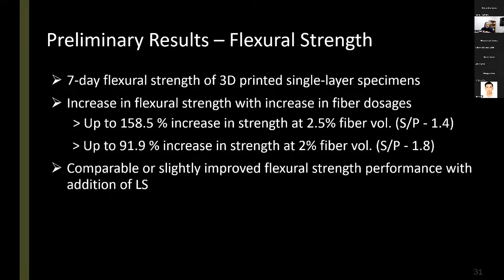So for the mixtures with sand to powder ratio of 1.4, we were able to get up to 160% increase in flexural strength. And for the group of mixtures with sand to powder ratio of 1.8, we got up to 92% increase in flexural strength only after 7 days of basically storing these samples in the lab.